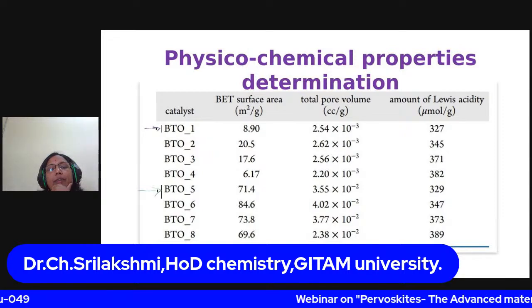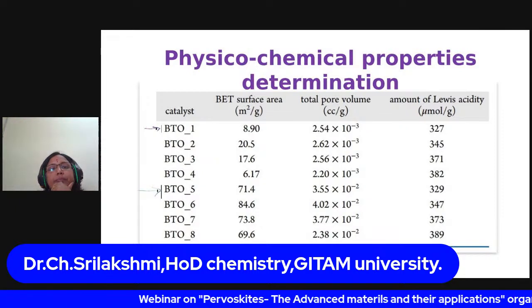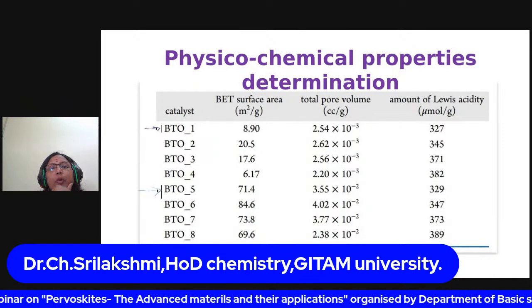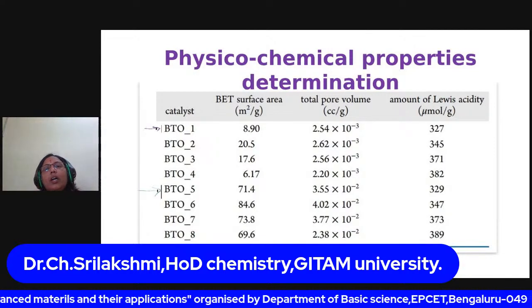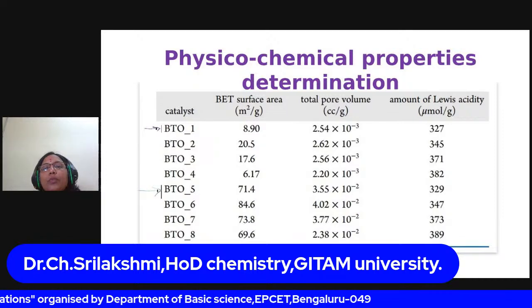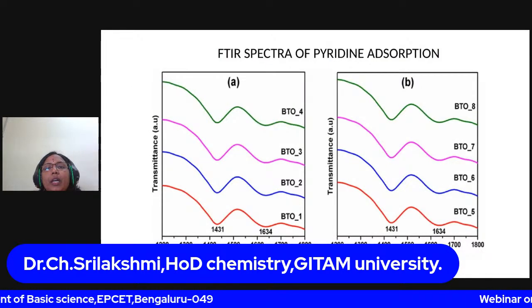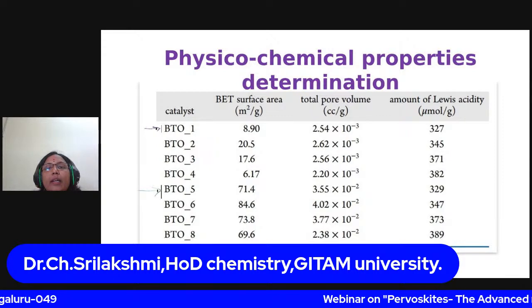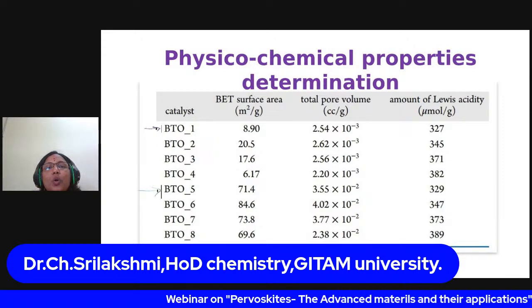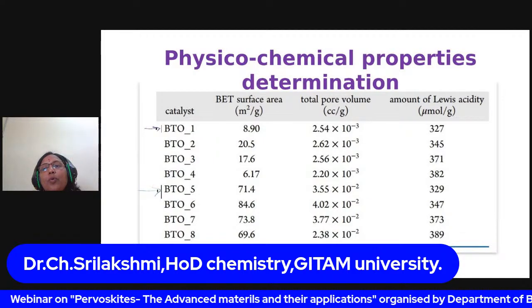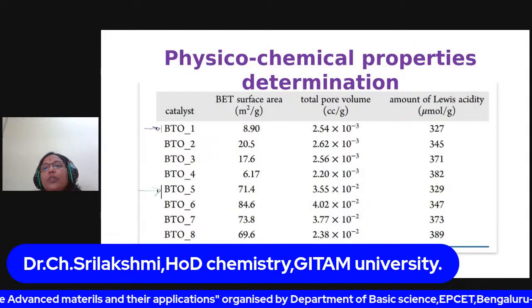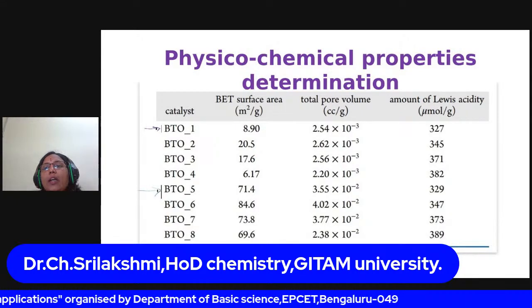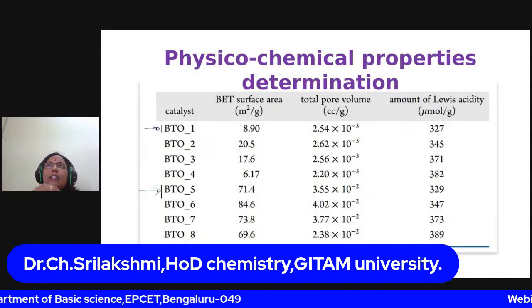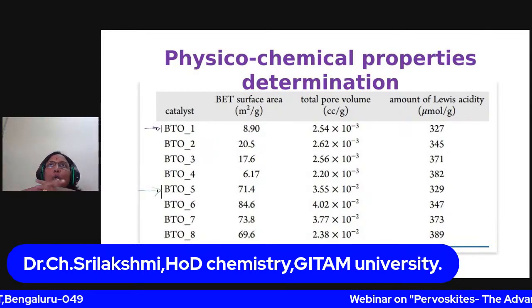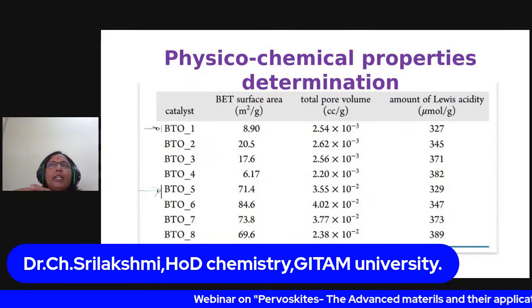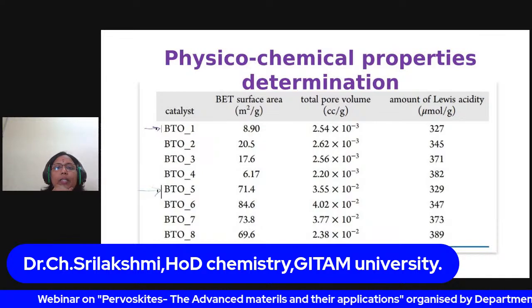So this surface area increased until 0.5, and after that it shows a decreasing trend. The same is the case with pore volume. You can see 2.54 into 10 to the power of minus 3, and here 3.55 into 10 to the power of minus 2. So surface area increased, pore volume increased. Let's see about the Lewis acidity. So this is 327 and this is 329. So acidity also increased. These results indicate that if you use a proper low temperature method, you can always synthesize the material with good physical and chemical properties.